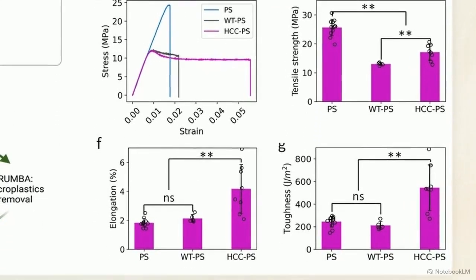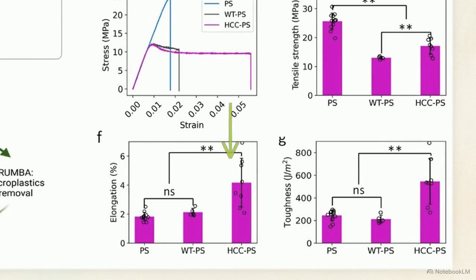However, Sections F and G reveal the biopolymer triggers a 2.3 times increase in elongation and a 2.2 times increase in toughness compared to pure plastic. The process circumvents the generation of a toxic waste stream by upgrading the mechanical tolerances of the recovered polymer, yielding a durable, high-value composite material.